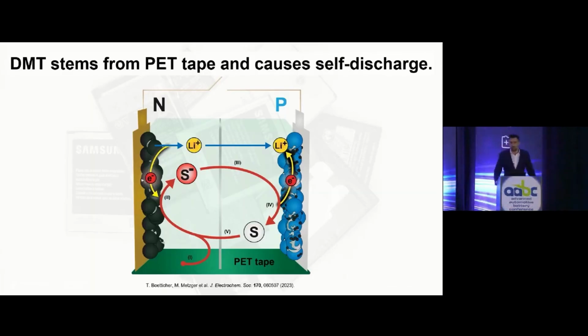So a quick summary of what's happening in our cells is, we have PET tape in our batteries. It dissolves to create this DMT redox shuttle molecule. The molecule can diffuse to the negative electrode. It gets reduced, changes its color to a red color. And for every molecule that's reduced at the negative electrode, for charge neutrality, a lithium ion has to leave the negative electrode, right? So then the shuttle molecule diffuses to the positive side and it gets oxidized. So you take away an electron, and for every molecule that's oxidized, a lithium ion needs to intercalate into the positive electrode. So if that happens over and over again, this redox shuttle reaction, then what you're doing is you're shuttling lithium from the negative to the positive electrode. So that's a self-discharge reaction, right? That's what happens on discharge.